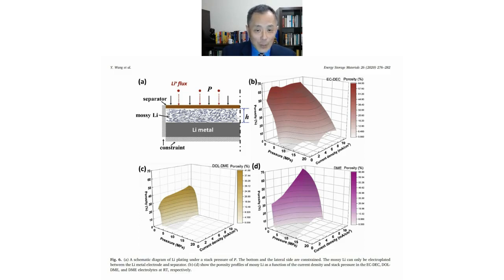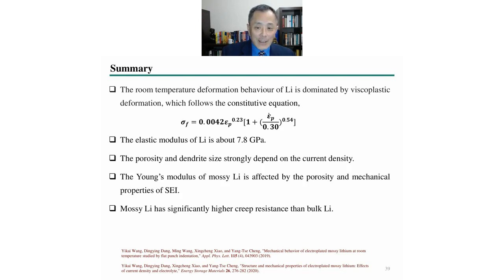So to summarize this part of our study, we've shown that at room temperature, the main deformation mechanism for lithium is viscoplasticity, and we proposed a constitutive relationship for metallic lithium. We determined the modulus of lithium foil, and we also showed the mossy lithium modulus is lower than that of the metallic lithium foil, but mossy lithium is more creep resistant. These measurements will help us to determine what kind of pressure one needs to apply to the battery cell if we want to use lithium as the negative electrode.